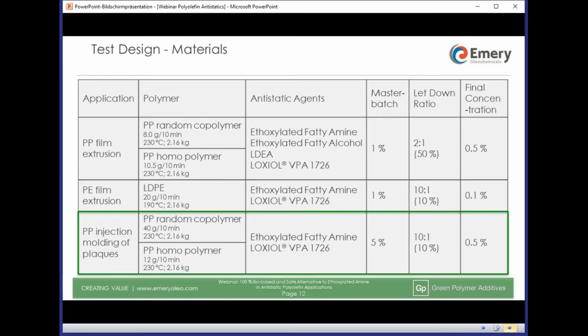Finally, we did injection molding, again with two different PP grades. The master batch concentration was higher in this case, as the extrusion and injection system in the injection molding machine caused a better mixing than in lab extrusion, so we could use a master batch concentration which is a bit closer to what is done in the real world. Important to mention, we always used the same polymer for master batch preparation and extrusion or injection molding, so we avoided any influence of blending polymers.